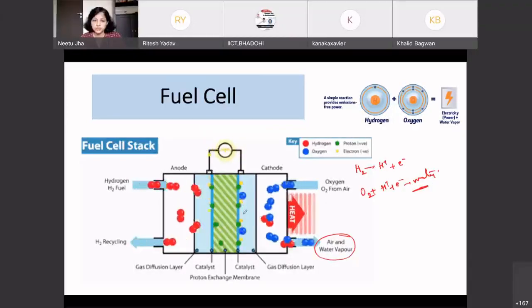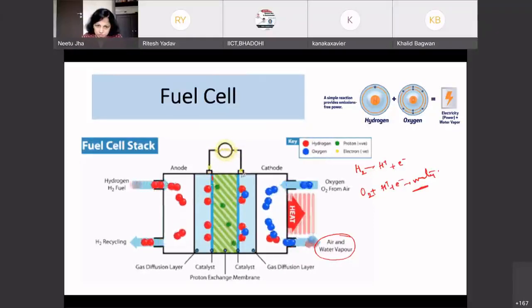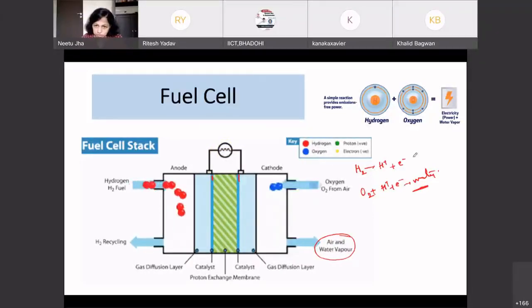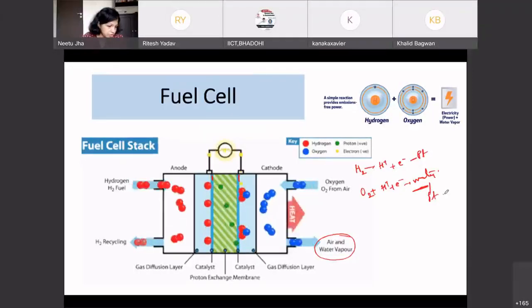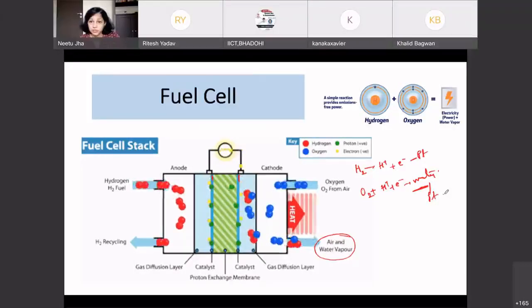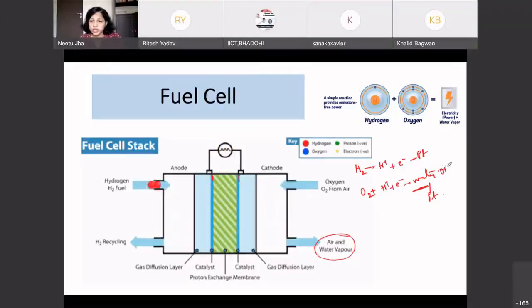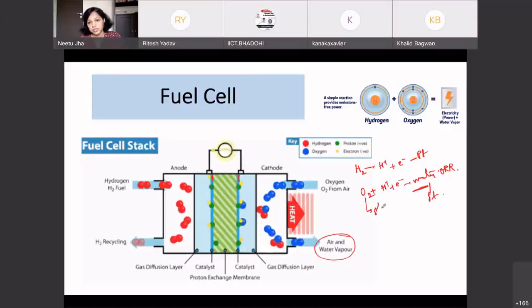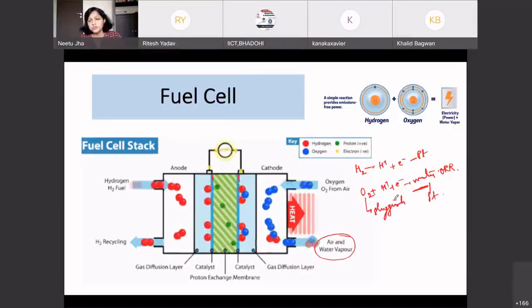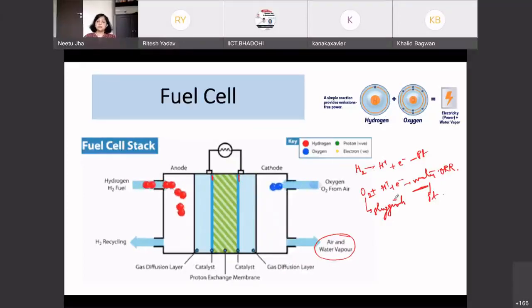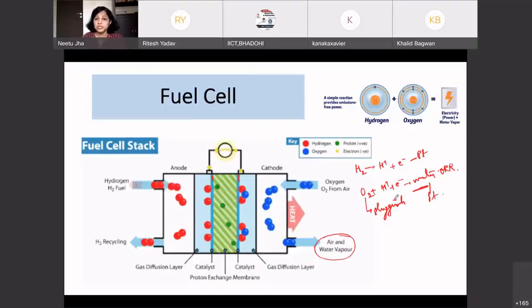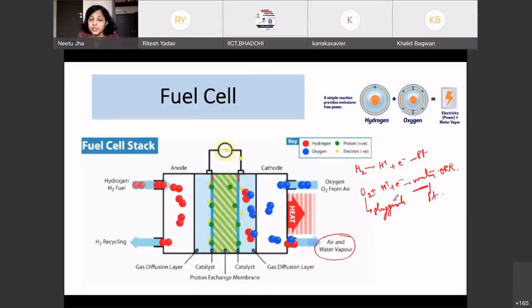But what are the issues here? This catalyst layer which you see at anode and cathode, for both the reactions, platinum is the catalyst. Platinum is the best known catalyst for oxygen reduction reaction and for hydrogen oxidation reaction. Hydrogen oxidation reaction is good to handle because it is fast, but the oxygen reduction reaction is sluggish in nature. So you need to improve the reaction kinetics of oxygen reduction reaction. How can we do it? We can do it by increasing the content of platinum, but again, platinum is very expensive.